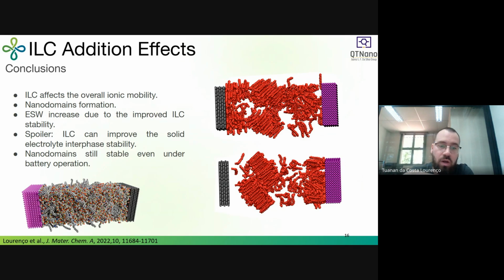When you look at solid polymers, this contact is not a problem anymore because they have some kind of liquid behavior, so the wettability is better. However, the stability will be lower than the ceramics. So going from liquid to solid, we can increase the safety. Maybe we can increase ionic conductivity, but we can also have problems with the contact between the electrode and the electrolyte. So you need to evaluate each technology, each material, and how you can deal with these problems.